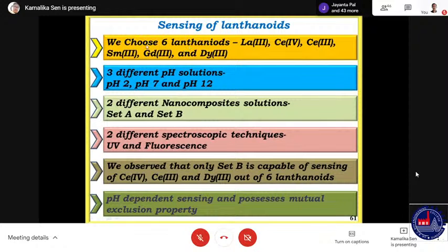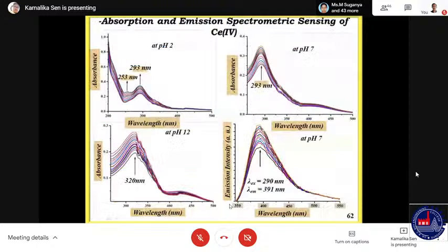And for the sensing case, we have chosen six lanthanoids: lanthanum 3, cerium 3, cerium 4, samarium 3, gadolinium 3, and dysprosium 3. You know how difficult it is to collect different lanthanide salts. Either they are too costly or they are not available in the market. They are very difficult to isolate also. So we could gather only some of these salts, and we have used different pH solutions. We have used our set A and set B, and we have used only UV and fluorescence spectroscopy, and the lanthanoids for pH dependent sensing.